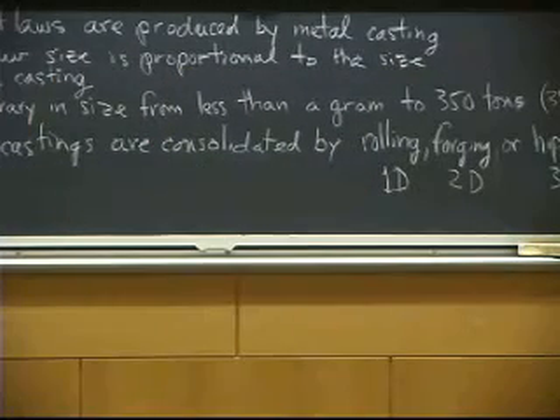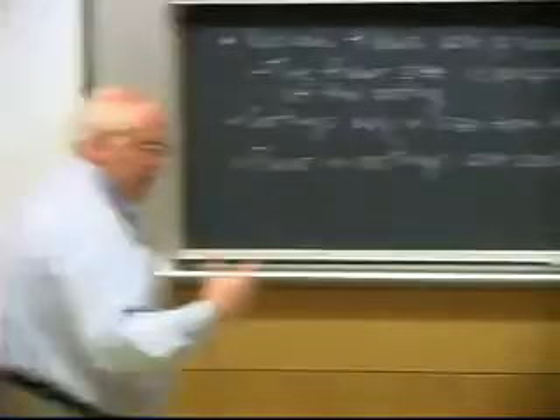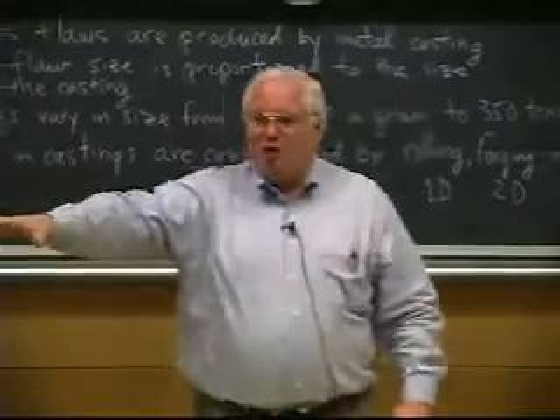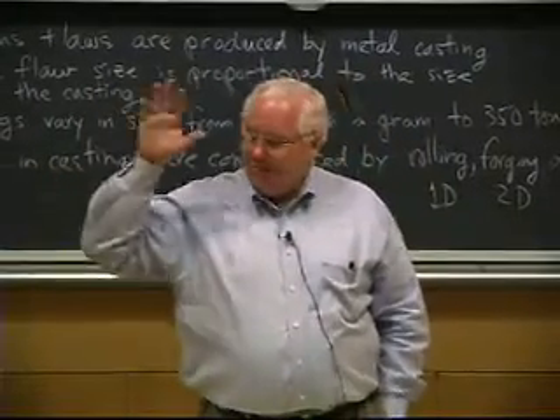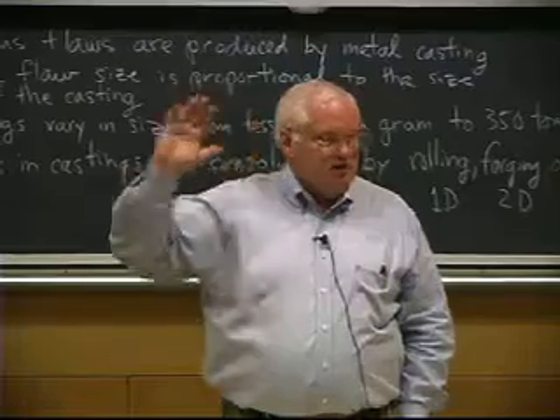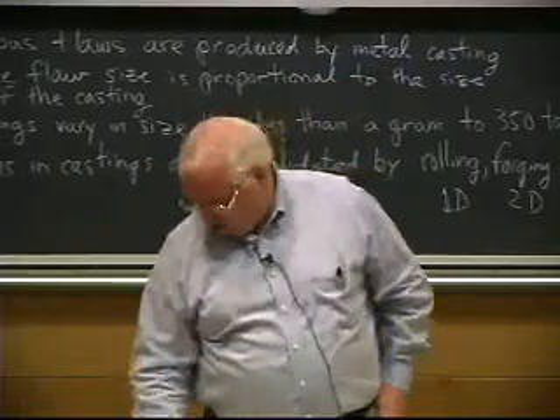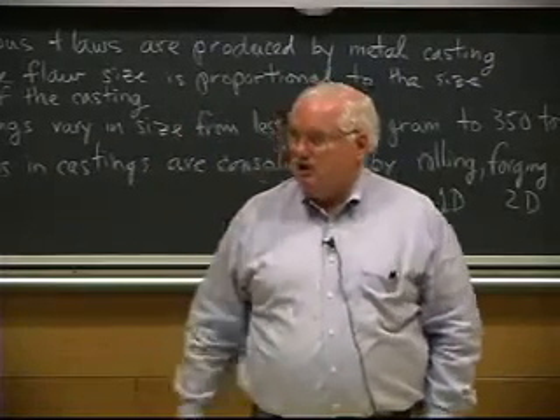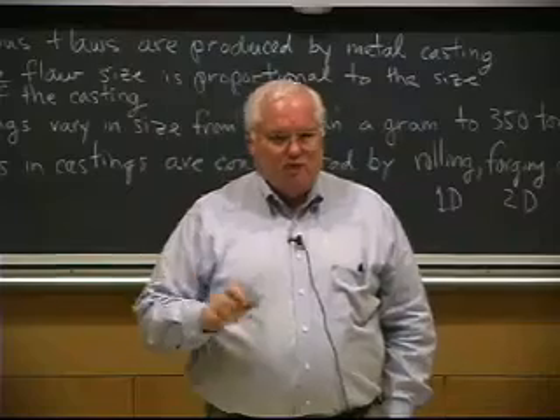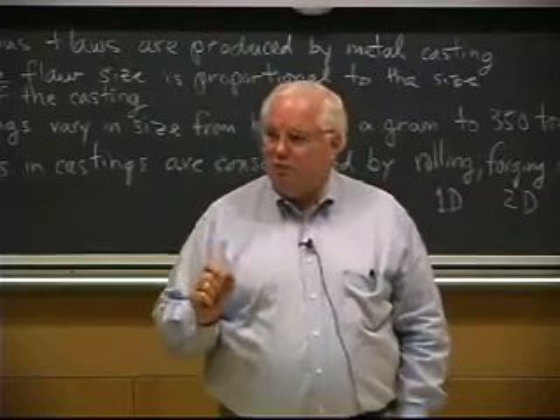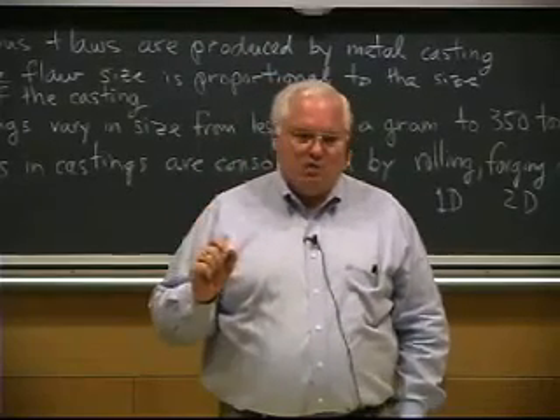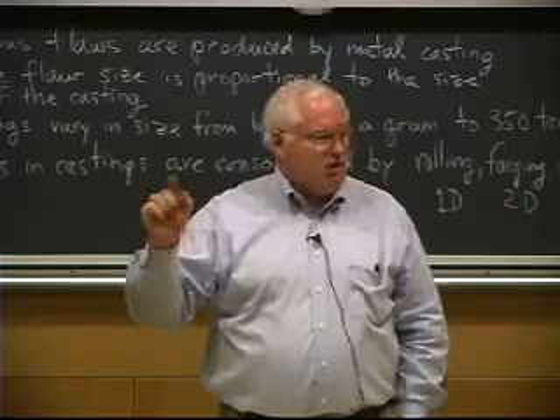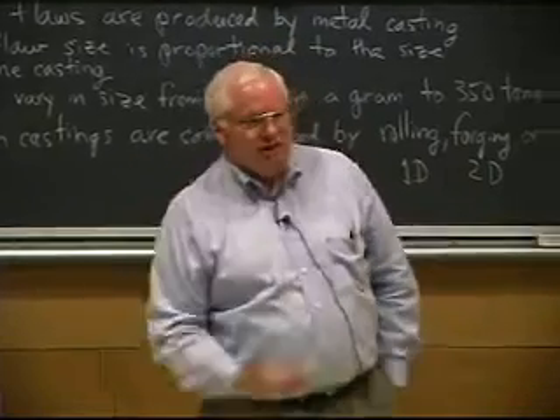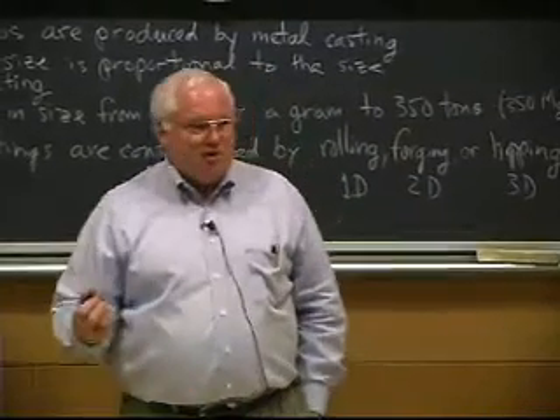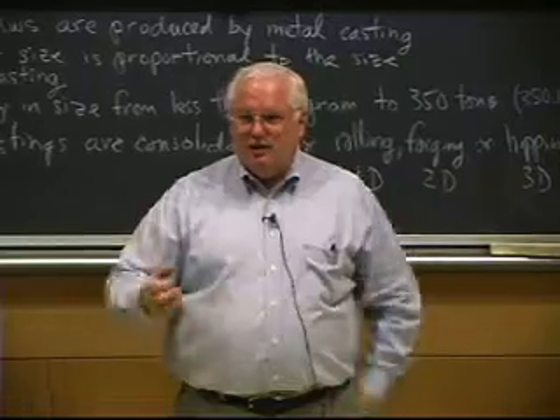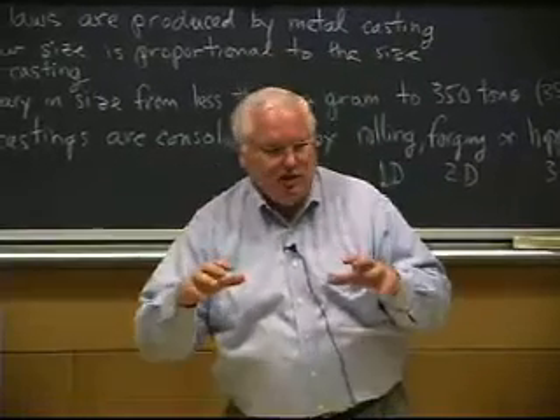IBM in the 1970s, when they were still making typewriters and little office machines and they had all kinds of zinc-based parts, had a huge program. This is when IBM was very, very profitable. Had a huge program to make zinc parts rather than die-cast parts for all their office machines. And they could form it at room temperature and get very good precision to form the parts, but they couldn't solve the problem of getting the grain size large enough that it wouldn't continue to creep at room temperature, just like the silly putty. So they'd put the parts in the office machine, and then over the next 6 months, all these precision parts would just kind of sag, you know.